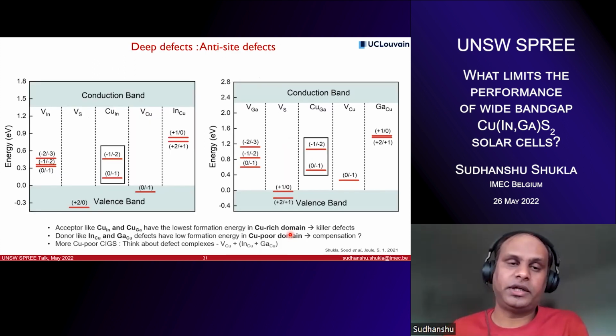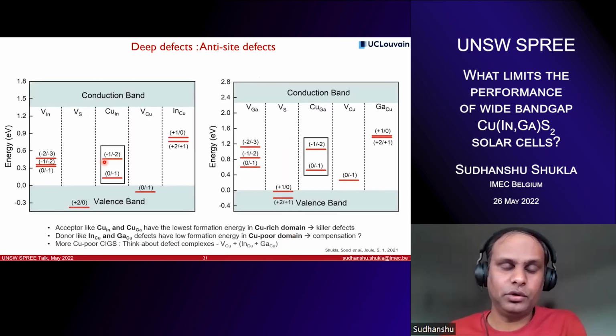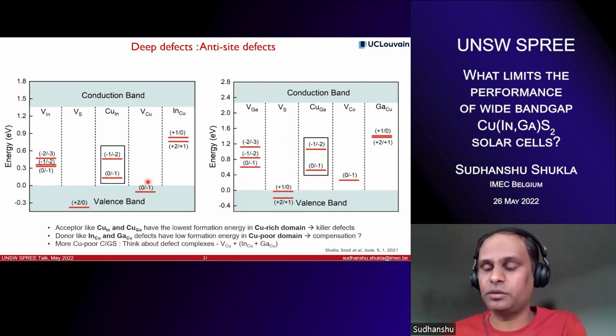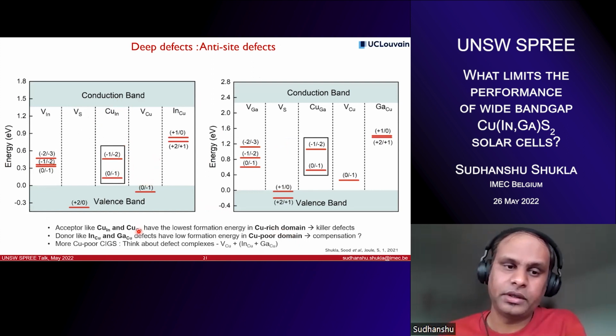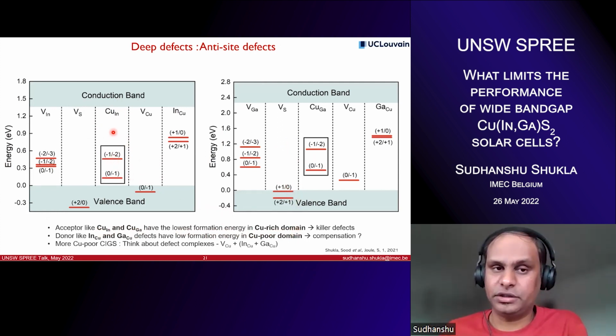And what are their locations in the band gap? If you look at their locations in the band gap, they form deep defects. So you have all the ingredients present to kill the lifetime of the absorber and limit the VOC. So you have these antisite defects, copper over indium and copper over gallium, which form in the copper-rich domain. As you move from copper rich to copper poor, what you basically do is you suppress the formation of these two defect culprits, copper over indium and copper over gallium.